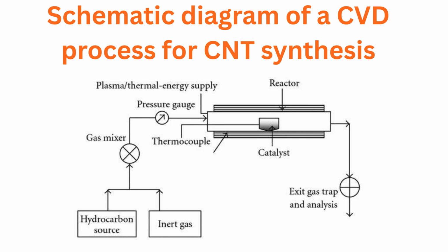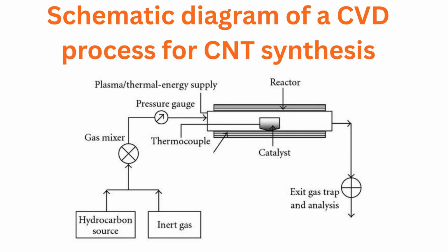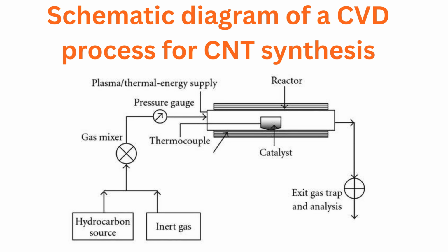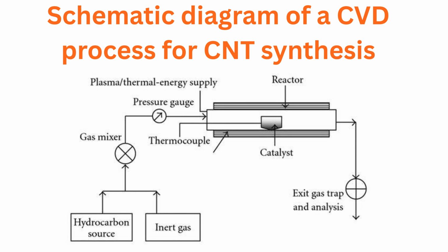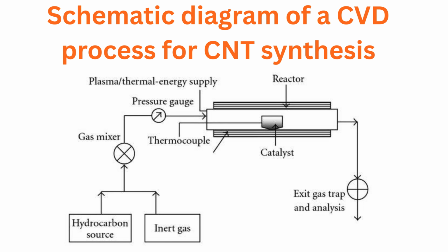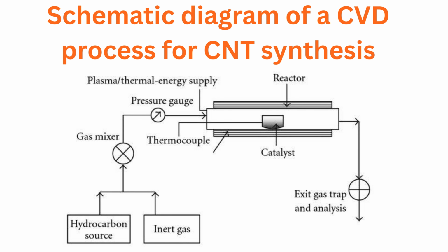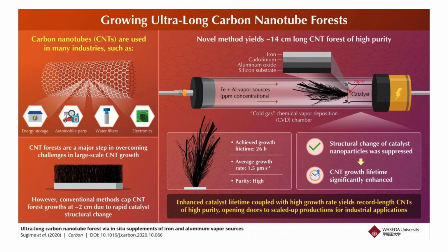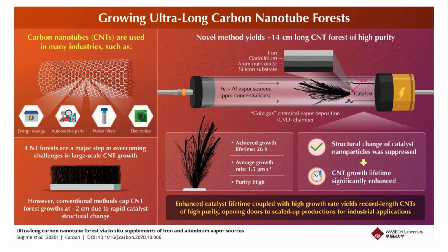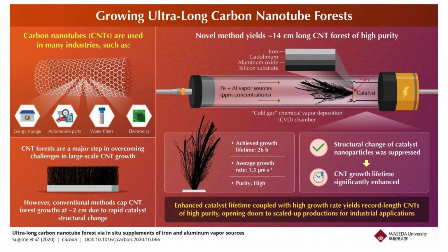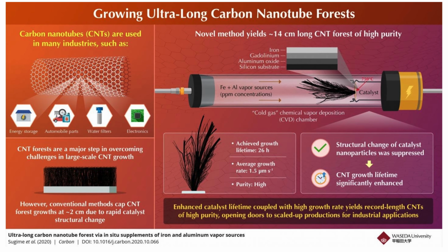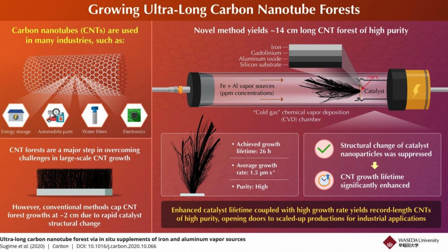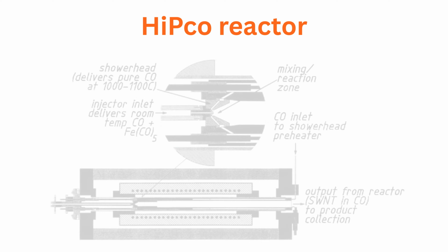In CVD, a carbon-containing precursor gas, benzene and acetylene in these early studies, flows over a substrate at elevated temperatures. Reactions between the precursor and the surface then lead to the growth of CNT from the surface. The degree of morphological control, adaptability, and scalability of CVD has led to it being the most common synthesis route for CNT today. An example of the control and scalability of CNT-CVD is the ability to generate aligned forests of CNT on a substrate consisting of catalytic iron nanoparticles embedded in silica.